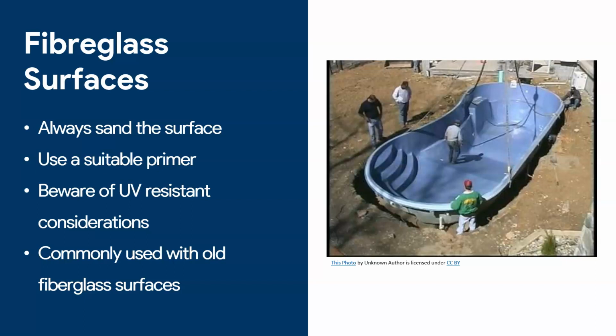As another comment, yes, epoxy will stick to the fiberglass, but make sure that you are considering UV resistance issues. So if you plan to use it for a pool, you may need to have always water in the pool. Otherwise, the sun will damage the epoxy, or you may want to apply a UV resistant coating instead. So this is obviously what I said before. You tend to recoat old fiberglass pools with epoxy. It's a very good way, for a low cost, to make your fiberglass pool look like new again.